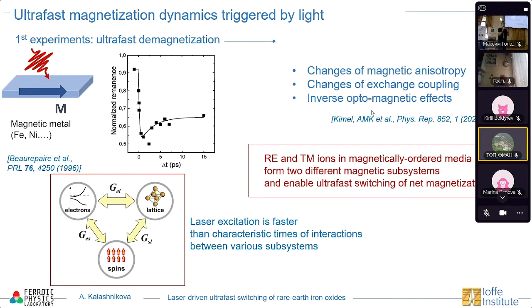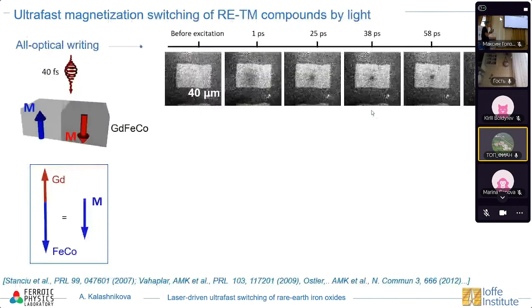which have different subsystems, for example, different magnetic ions, and these magnetic ions couple differently to the lattice or to light. So, from this point of view, magnetic materials which have magnetically ordered rare earth and transition metal ions are extremely important and extremely interesting materials. And actually, this kind of combination allows us to realize, for example, switching of magnetization by light. First, I will very briefly introduce probably the most famous experiments in this field, but I will not go into details because it's about metals, so it's really far from the subject of the symposium.